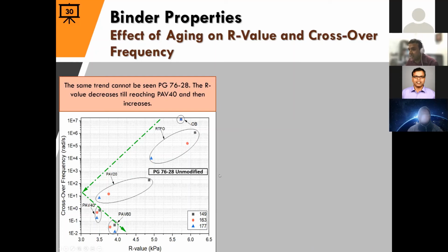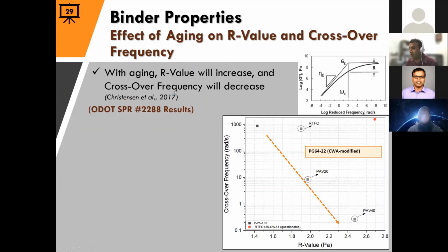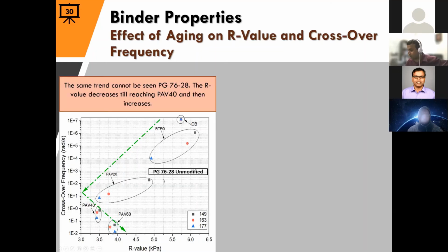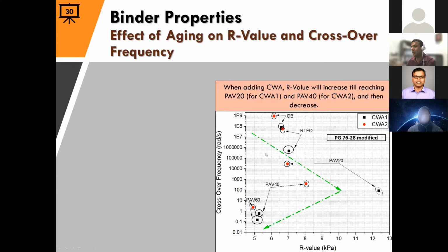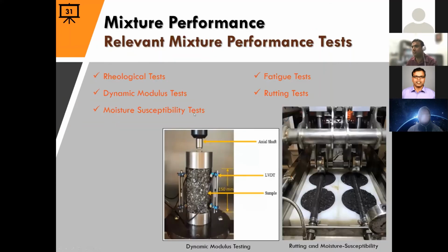So that basically means that these traditional R value based analyses are not going to work for these polymer modified materials, because the crossover frequency for the polymer may actually be different from the binder itself, right? So there is a lot of analysis going on. We're actually working on a paper based on some of that analysis. I'm going to skip over this.